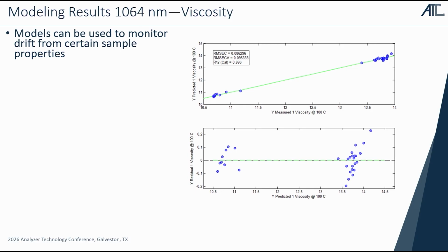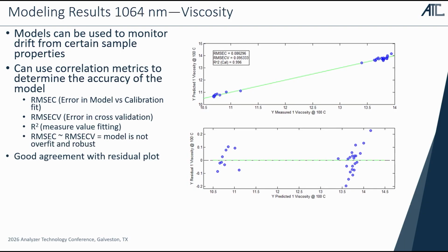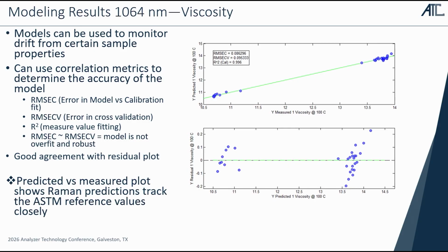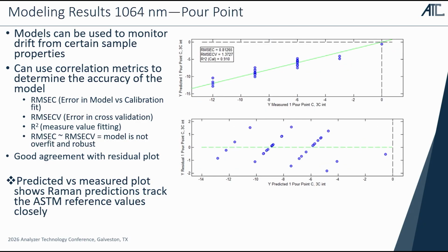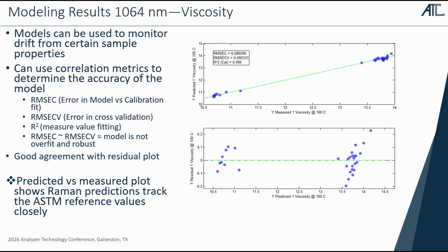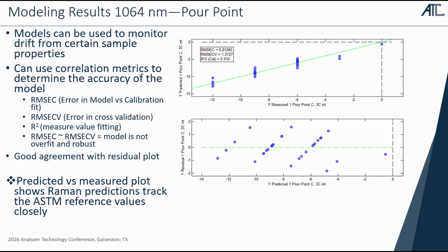And then to move on to just some very basic modeling that we've done with 1064 as well. You can see that we have really nice agreement with our modeling results for chemical properties such as viscosity, and we also have good agreement with the residual plot as well, which is telling us that our model is agreeing nicely with some of these known metrics, and that it is essentially displaying that 1064 is a viable option in terms of building some of these models. And so that previous slide I was showing is just for the predicted modelability of the 1064 results for viscosity, and then also has a good agreement with pour point as well, with decent R-squareds, and then good agreement in the error variability as well.